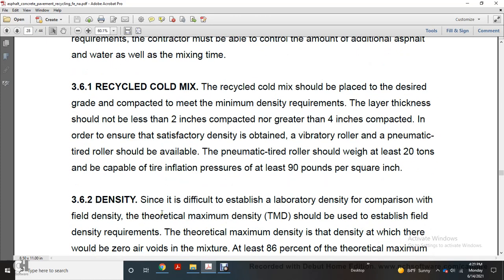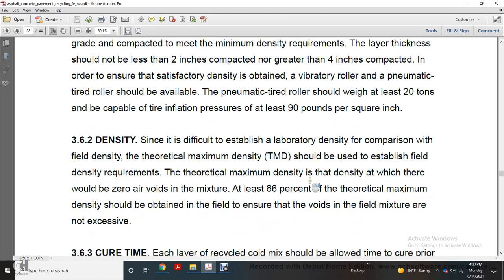Recycled cold mix. The recycled cold mix should be placed to the desired grade and compacted to the minimum density requirement. The layer thickness should not be less than 2 inches compacted and no greater than 4 inches compacted. In order to ensure satisfactory density, a vibratory roller and a pneumatic roller should be available. The pneumatic tire roller should weigh at least 20 tons and be capable of a tire inflation pressure of at least 90 pounds per square inch.